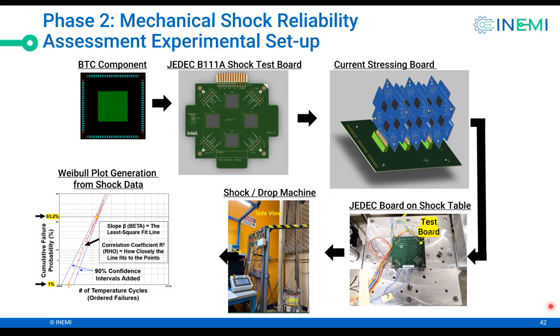And then we set the board up on a shock table and we drop it, and then we collect the data wherever we get a failure. The number of shock drops, and then we plot the probability and try to see if there is a variation in the characteristic life as you migrate the bismuth towards one end of the solder joint. So that's the mechanical shock reliability experimental setup. Next one.